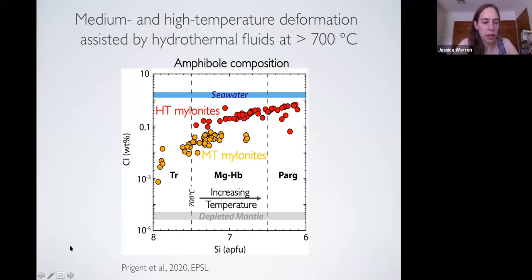So we've also looked at, so I don't have the images in this presentation, but Cécile Prigent has done some imaging with SEM to look at essentially the 3D structure on the surface of the grains, and has imaged porosity and also some dissolution pits as well. And actually, we've taken as a guide a lot of the work that's been done on continental mylonites, looking at the porosity in those. And we're seeing very similar features in these prototype mylonites in terms of those kind of etches and things on the grains that have been observed in continental mylonites that have seen fluid flow.